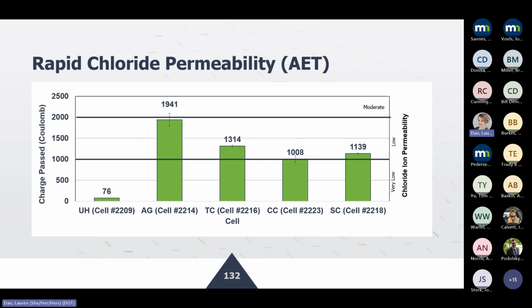And quickly looking at the RCP test, people still do the RCP test. It might become extinct in a few years. Maybe the bulk resistivity testing might replace this. But anyway, this test was performed, and as you can see, for ultra high, very, very low permeability, corresponding with high resistivity, as I will show you on the next slide. And overall, all these mixtures are within the low to very low permeability range.